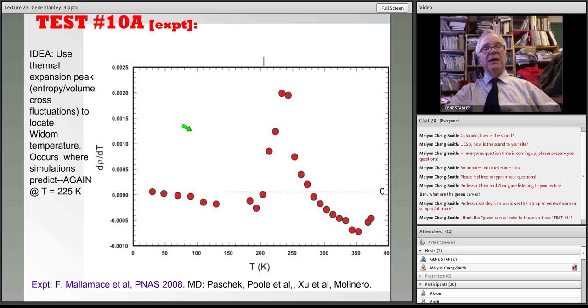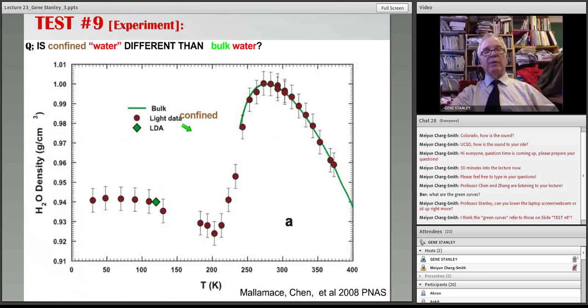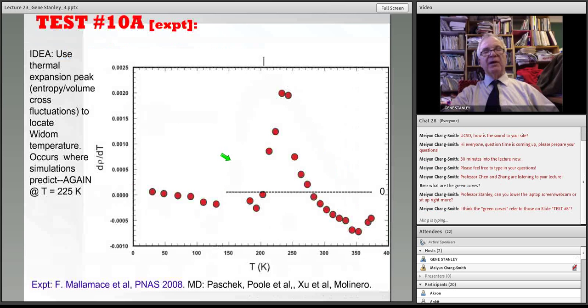Go beyond. So here is now the derivative of that curve. The derivative, you remember, was called the coefficient of thermal expansion. That derivative is, as you can see, negative here, then it becomes 0, and then becomes positive. So what we plot here is the coefficient of thermal expansion. It's negative, negative, negative. It becomes positive and goes up, and then it has a maximum just when the system crosses the Widom line at about minus 35. And then it comes down again. And as you saw, it crosses through zero at 205 Kelvin, which is the temperature where the density actually starts to increase again on further cooling.